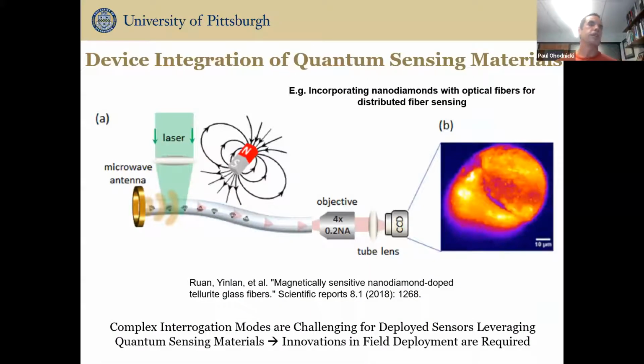One big challenge, though, is if we take some of these new and emerging quantum sensing materials and we try and integrate them with practical device platforms, that integration is not trivial. And so this is an example reference, and this is really good work. I like this reference, but it's very difficult to envision this type of scheme in some type of distributed sensing modality, for example. So here's an optical fiber. It's a tellurite glass fiber. It's been doped with nanodiamonds, which have nitrogen vacancies, which can be used as qubits. It's being illuminated with a laser exterior to the fiber, as you see.